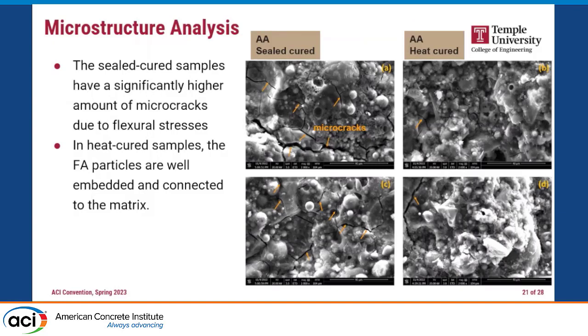I'm going to skip this one. We looked at the SEM images after the flexural experiment. At the left side, alkali activated seal cure, right side, alkali activated heat cure. You see a lot of cracking in the case of the seal cure, which makes sense, right? We have low strength for the seal cure one. The main reason we observe here is that due to the heat curing, we get higher dissolution of the fly ash particles as well as the slag particles, and we get a more cohesive and uniform structure. Even unreacted fly ashes or slags are embedded inside that matrix, so that helps to improve the strength of the system.